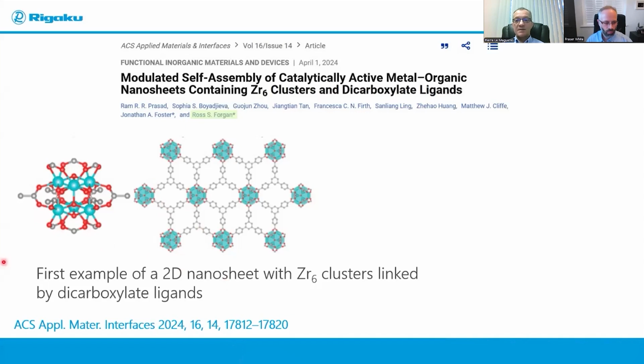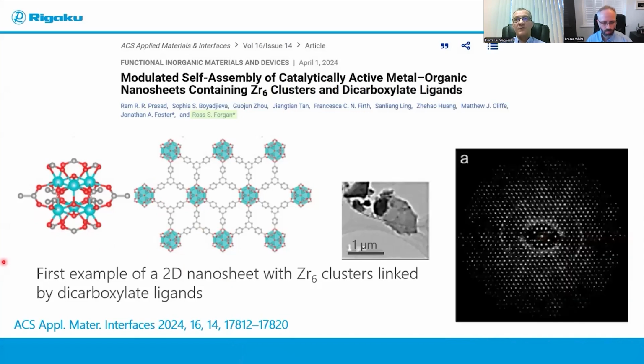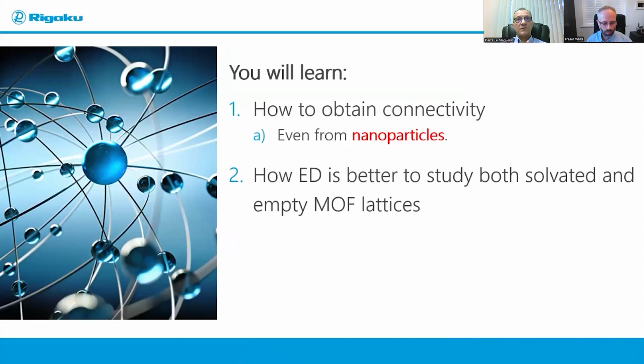And the problem here was that they could not characterize the different MOF compounds that they were synthesizing in the course of their synthesis attempts, because they could not grow crystals for X-ray crystallography. And again, electron diffraction saved this project. Here is a picture of crystallites or small particles they used, and an example of a diffraction pattern they got from this.